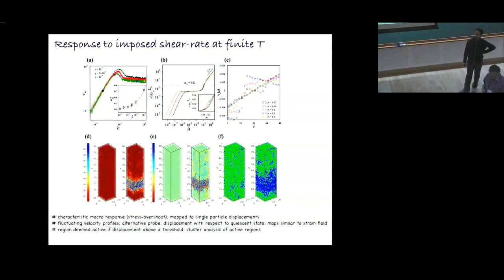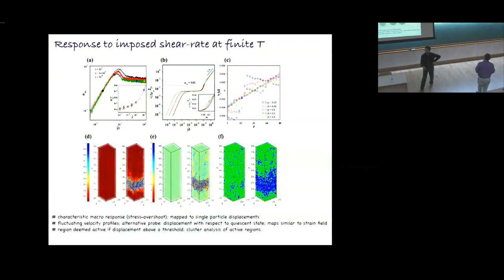What is the mechanism or microscopic picture of onset of these hotspots? That's a million dollar question. If I can answer that, then I'd be very happy. A lot of people would be happy. What we'd like to understand is, is there a structural origin to these hotspots? So far, there is no conclusive agreement. Different people say it's already encoded in the structure that I'm shearing. But others will tell you that it's actually those hotspots are emerging as you are shearing the system. As it's closing closer towards the yielding point, basically these zones are emerging more and more. It's a combination of basically shear and temperature that could decide where the hotspots would emerge. In fact, they're stochastic in the sense that if you take a thermal system, you can take the same initial state, you can run with different sets of velocities, and you can see that the hotspots emerge at different points, spatial points. Can they be thought of like rare fluctuations? In some sense, you could think of that. Yeah, why not? Okay, I guess we have to move on. So thank you again, Pinaki. Thank you.